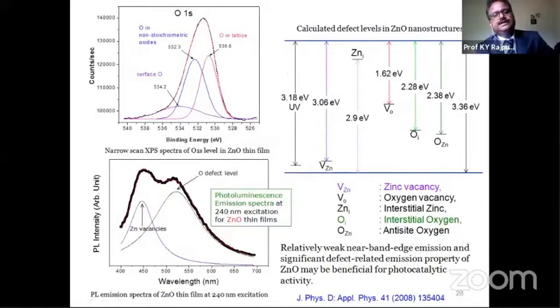The high conductivity of this oxide. If this zinc oxide is in perfectly stoichiometric form, then it is insulating. It is an insulator. But if it is non-stoichiometric, if there are deficiencies, then it becomes conductive. So we discovered the cause of the conductivity. It is found that the oxygen defect levels and zinc vacancies are responsible for the high conductivity of the zinc oxide.